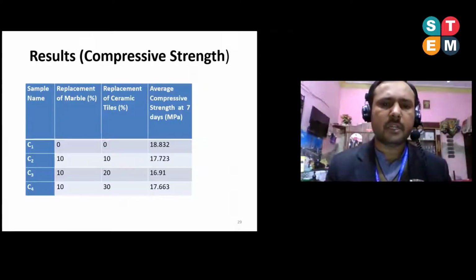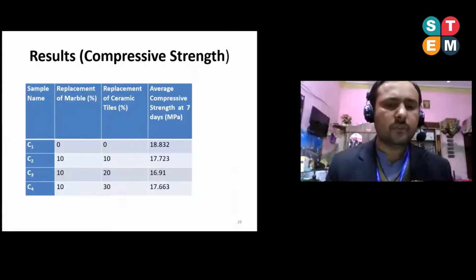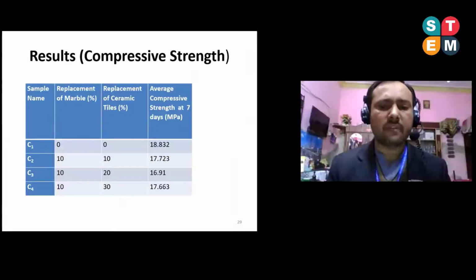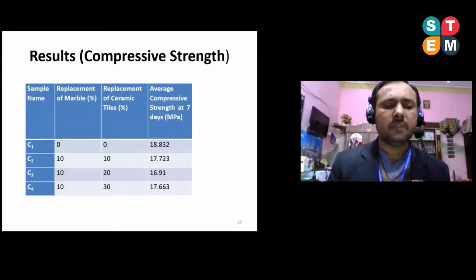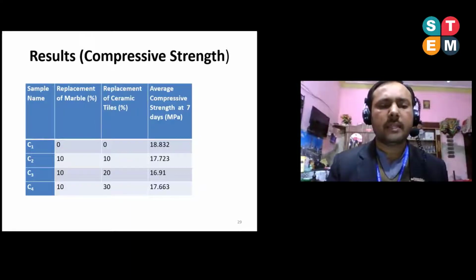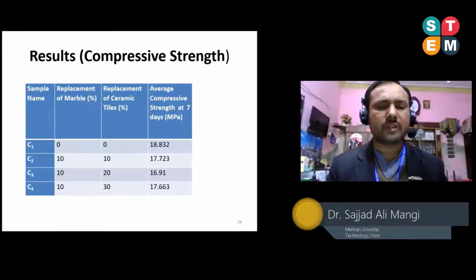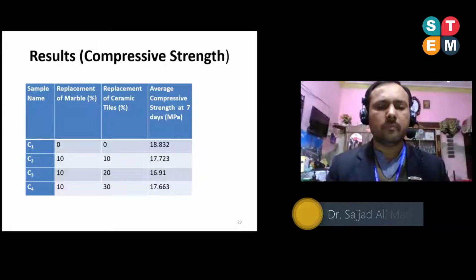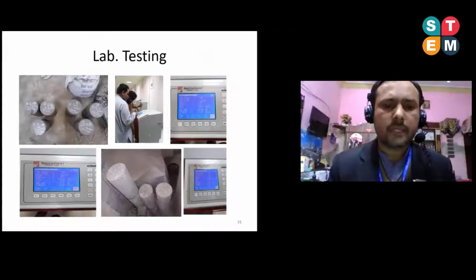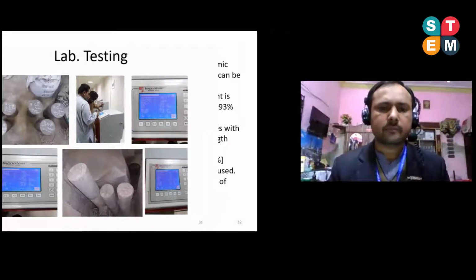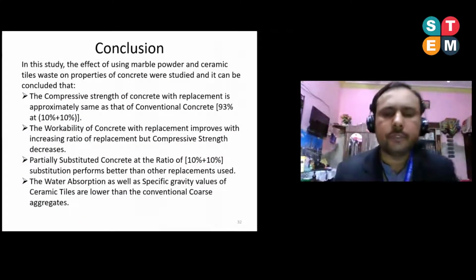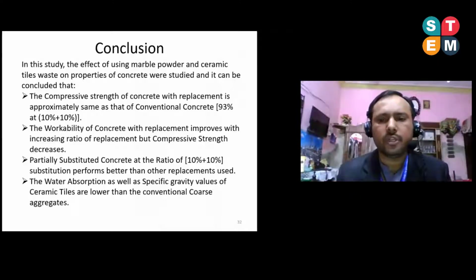So these are the results, main results of the compressive strength test. C1 without any waste gives the compressive strength at the age of 7 days 18.832 megapascal. C2 17.72 megapascal. C3 16.91 megapascal. C4 17.66 megapascal. At the 7 days or the initial age of curing, and it shows the strength is going to be decreased as compared to the control mix. But at the age of 28 days, sorry. So these are some tests, some snapshots during the compressive strength test. So this result shows when we increase the duration of curing, it will give the good strength.